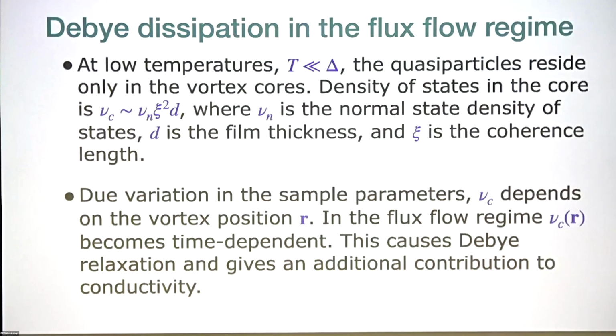Okay, let me start with the simplest example of the appearance of the Debye relaxation in the flux flow conductivity. Let me consider the low temperature regime, T much smaller than delta, where the quasi-particles reside only inside the vortex cores. So then this vortex core can be considered as a zero-dimensional system where the density of states is essentially the density of states of a normal metal. So the density of states per vortex is the normal state density of states times the volume of the core, which is xi squared times d, where d is the film thickness and xi is the coherence length.